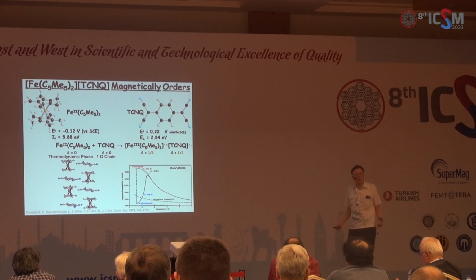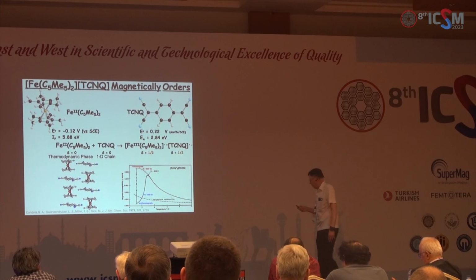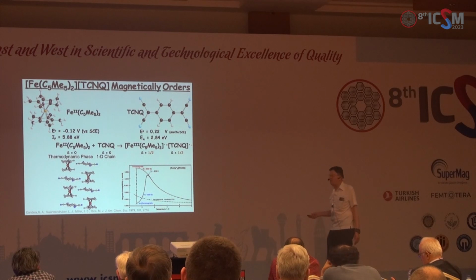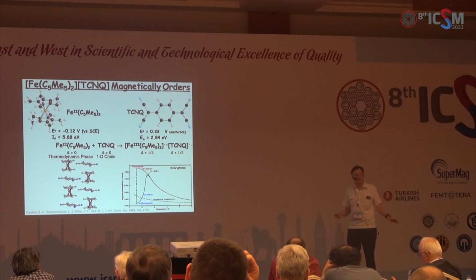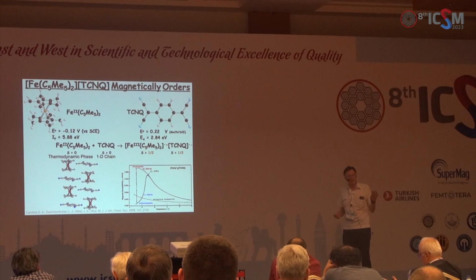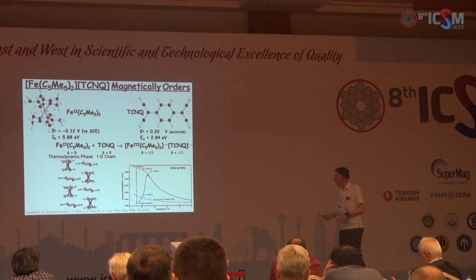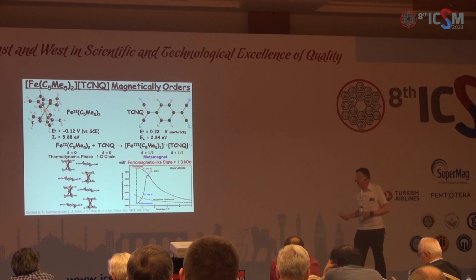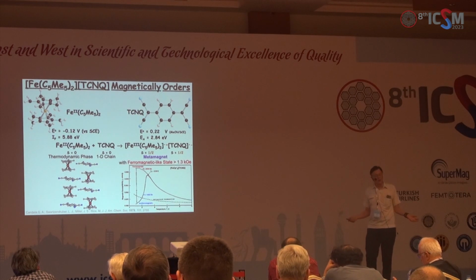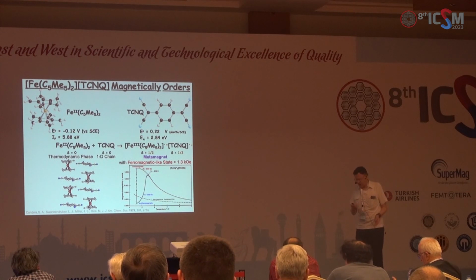But if you do the same experiment at 2,000 Gauss applied field, it goes up, stays up, we take it down to 60 millikelvin, never comes down, and acts like a high moment ferromagnetic state. Ultimately, we studied this in painful detail and determined that it is a metamagnet that switches between the antiferromagnetic to the ferromagnetic state at a critical field of 1,300 Oersteds. So it's magnetically ordered, but with an antiferromagnetic ground state for this material.